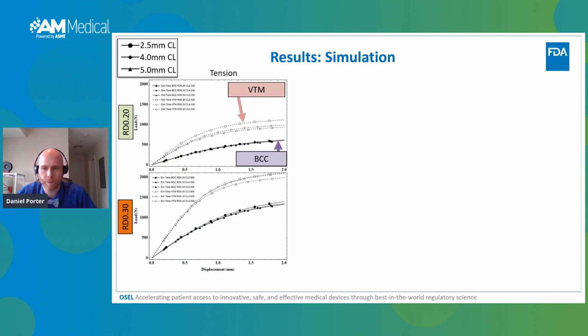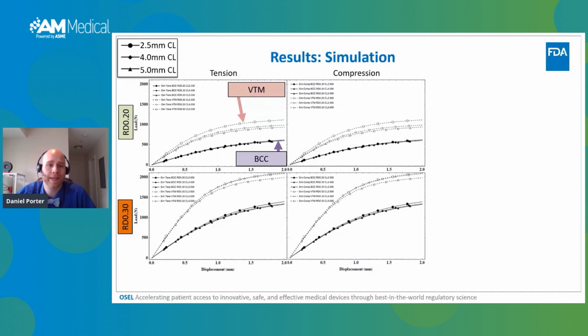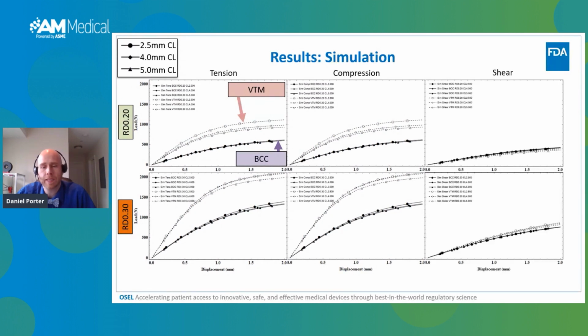simulation results. Overall, in tension, compression, and shear, we obtain pretty agreeable performance for a loading mode using a specific cell type at a given relative density. AKA, if you notice, all these black lines, even though they have different strut diameters, they all perform roughly the same, with the note that the Voronoi are a little bit different.